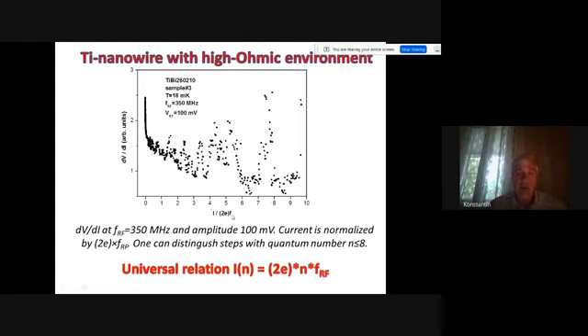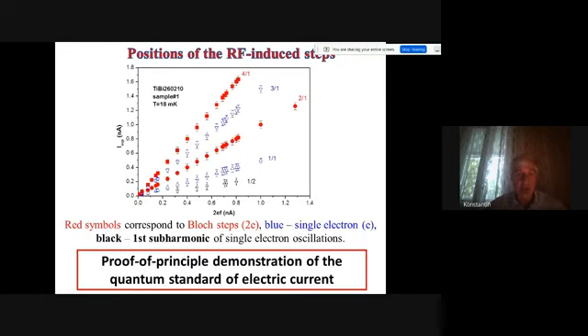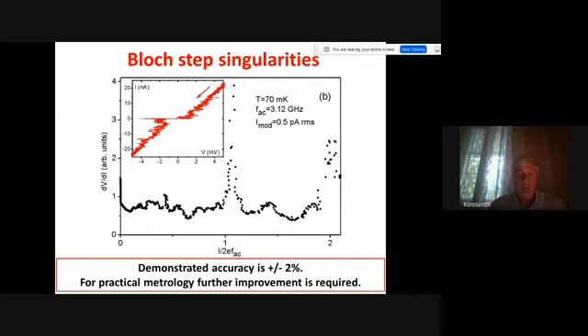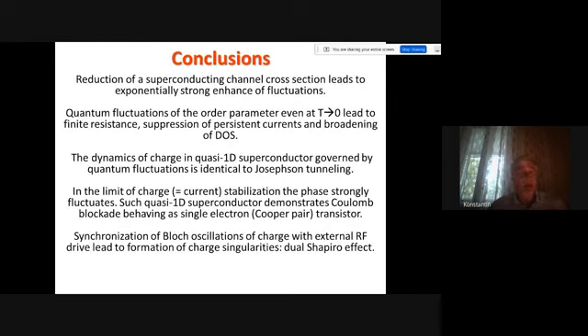On the next slide, I show the derivative of this IV characteristic in units of current normalized by the charge of the Cooper pair times frequency. So it's a universal relation showing that indeed there are quantized steps in such a system. And if we plot the positions of these quantized steps, they really follow the expected linear dependence. So it's a proof-of-principle demonstration of the quantum standard of electric current. However, they are not as sharp as desirable. So far we managed to obtain an accuracy of about a few percent. And for quantum metrology, it should be at least 10 to the minus 7. So that is the prospect for the near future: to improve the accuracy of these quantized steps.